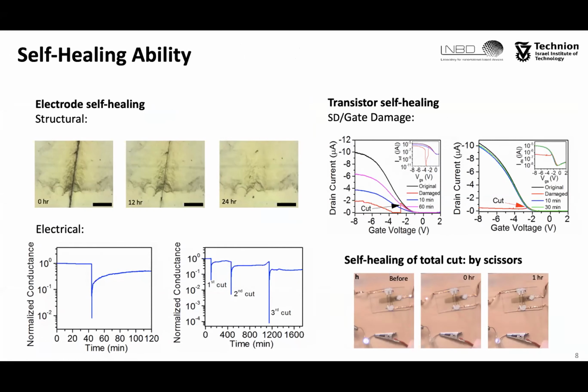The upper left figure shows optical images of the healing process of the structural damage after a blade cut made perpendicular to the conduction pathway. As you can see, the conductive film can recover from drastic cuts quickly and maintain good conductivity. In this case, the cut was 5 micrometers in width and 2 micrometers in depth.